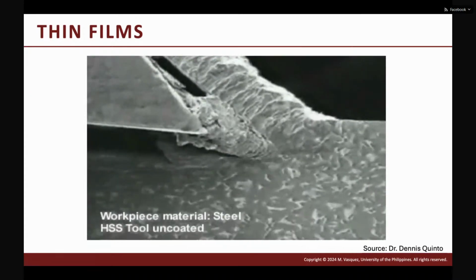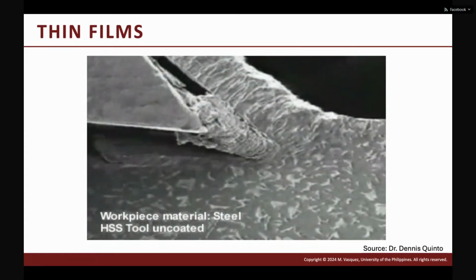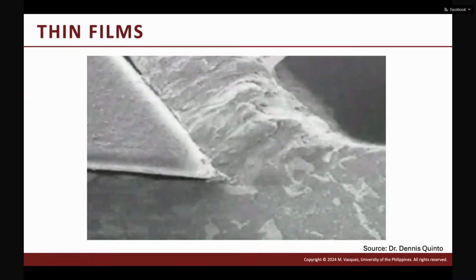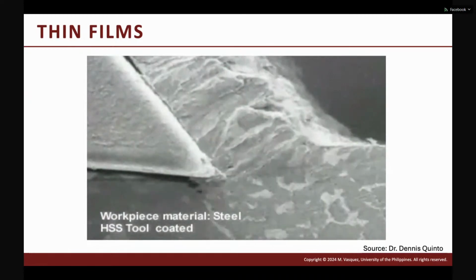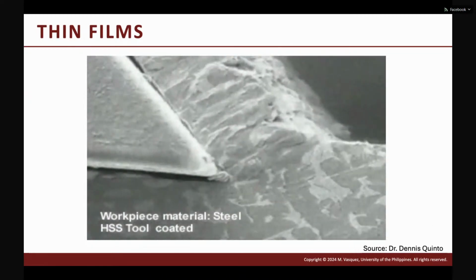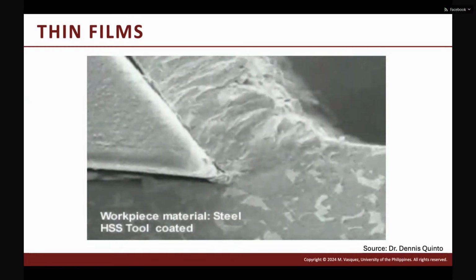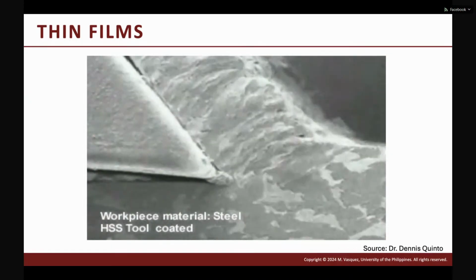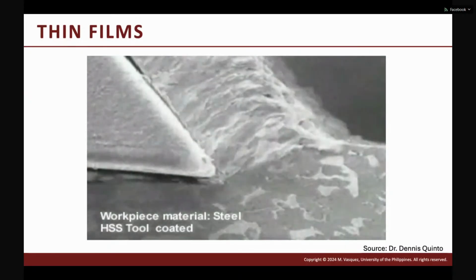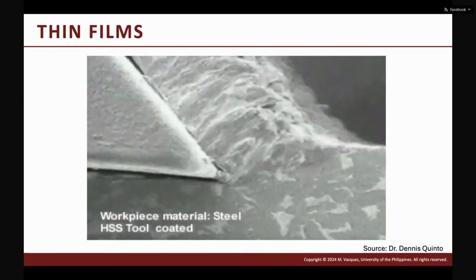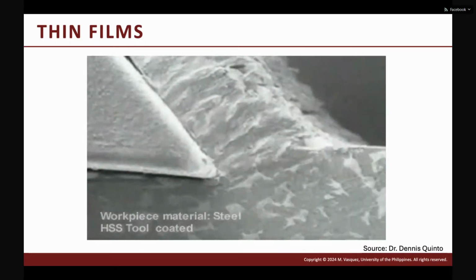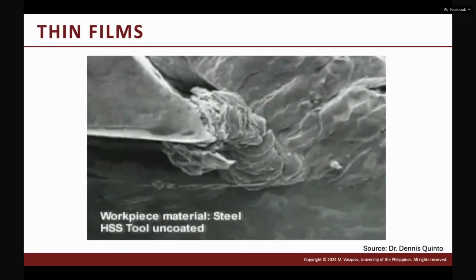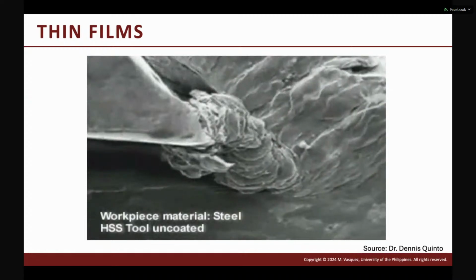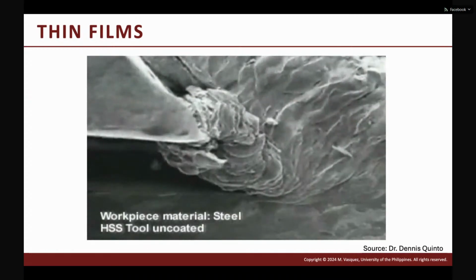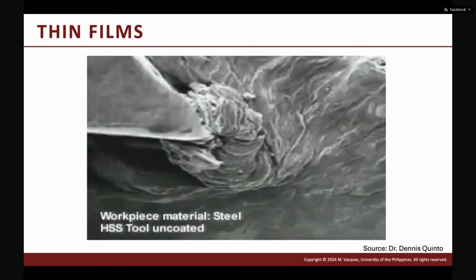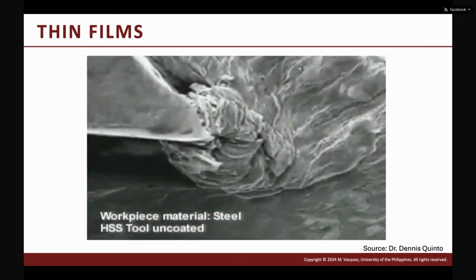And this makes the precision cut less precise. And eventually, because of the inefficient dissipation of heat, the material will break or fail. But with coating, so you have to choose the right coating, it can dissipate heat easily, as well as have a low coefficient of friction. So you will have a smooth cut, and that means that with coated tools, you can increase the lifetime of your tools, and that's where coating becomes important.